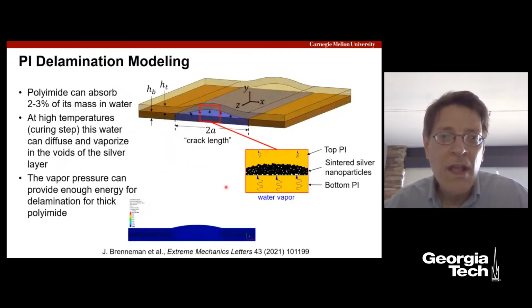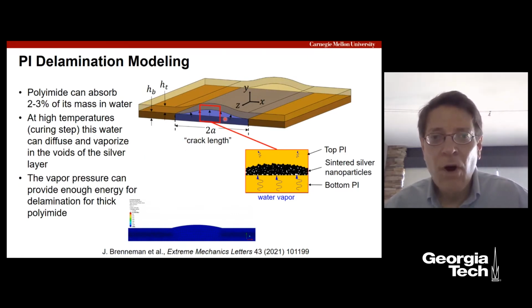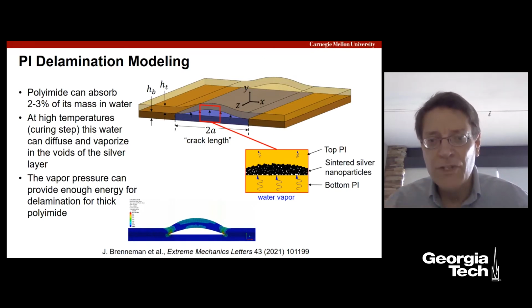So what in the world is going on? We did some modeling on this, and what we found was, of course, polyimide absorbs water, well known, a lot of water sitting in it. And at high temperatures, our hypothesis was the water is getting into the void where the silver nanoparticles are, and it's vaporizing and creating a vapor pressure, and that is creating the energy for cracking this. It turns out that's exactly what's going on. It isn't thermal expansion driven. This is driven from the vapor pressure, and we literally are seeing pressure build up in this cavity, and eventually it creates a crack propagation, and that's what's creating this issue.